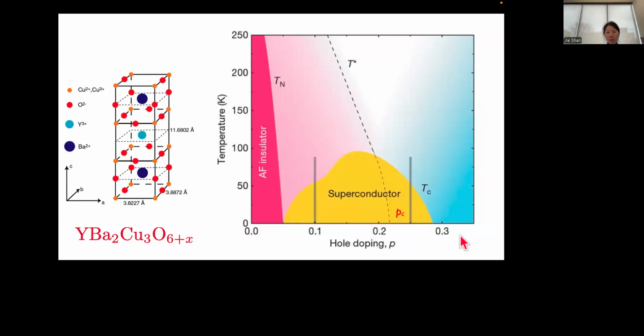So here on the horizontal axis, you have doping, which is just the density of electrons on a single layer of copper and oxygen. It's controlled by changing the oxygen concentration. And the vertical axis is temperature. So there are many things going on here. In fact, this is a highly simplified phase diagram, which is part of the reason it's taken 30+ years to make progress. I'm going to focus on the phases above this temperature Tc, which is the critical temperature for superconductivity, which you can see is as high as 100 Kelvin or 90 Kelvin in this material.